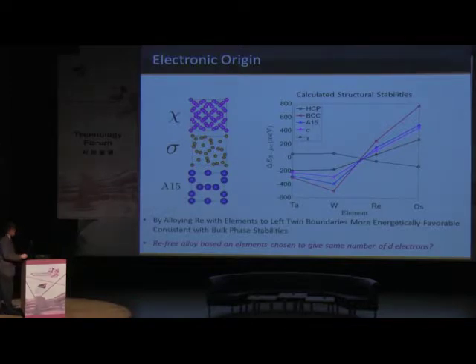So what this tells us is basically, and again, this came out of doing the high throughput calculations, if we can design an alloy now with an average d electron count, say somewhere in here, we're going to have this very easy twinning deformation possible. And so we think we can also control the ductility of the material. Okay. So again, this is a different kind of example rather than just screening through a bunch of properties. It's looking at more of a mesoscale type of phenomena related to twin deformation.